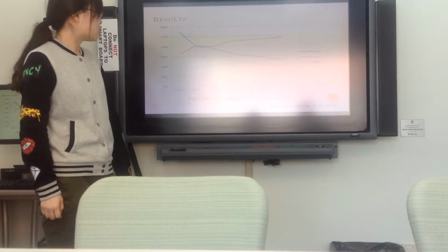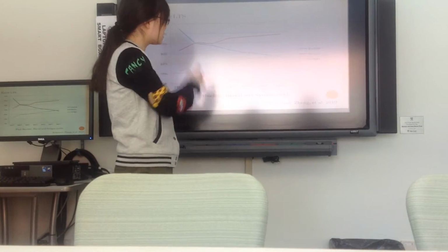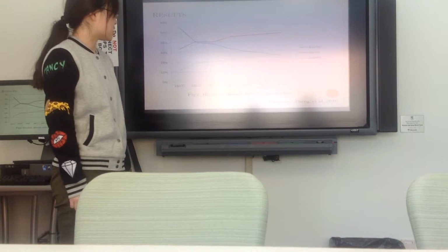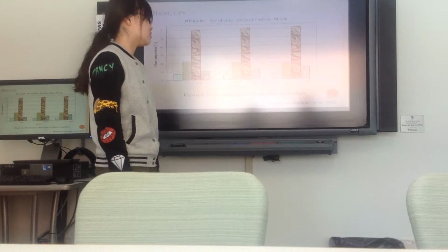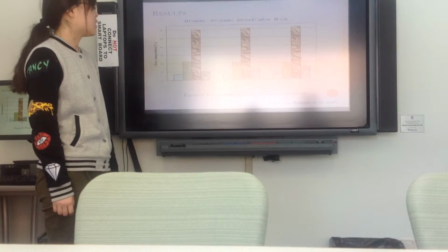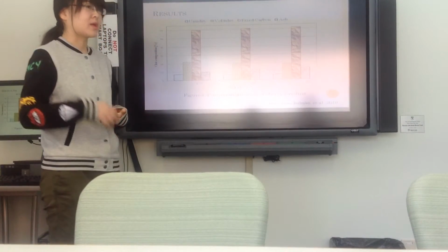There are some data from the previous study. The first one showed that the biochar yield decreases at increasing temperature because of decomposition of the biochar, and the syngas and bio-oil yield increases as temperature increases. This one is a proximate analysis of cherry stones at 3 different temperatures. It shows that the fixed carbon content increases with increasing temperature, but the volatile matter content decreases, so the biochar will become more stable when the temperature increases.